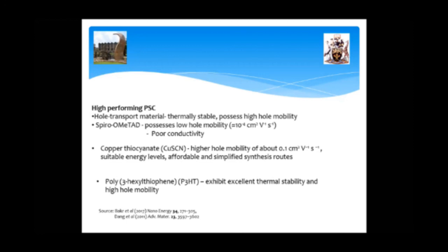Now, to address this, we propose to substitute spiro-OMeTAD with copper thiocyanate, which has a higher hole mobility of 0.1 square centimeters per volt per second.